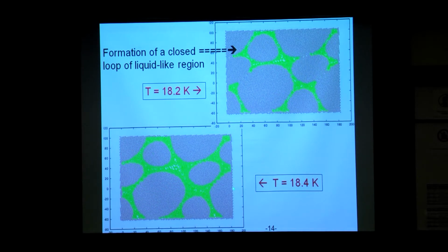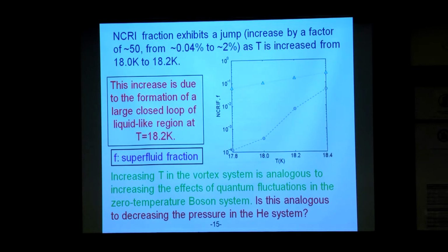As we increase the temperature even further, these loops get bigger, and if we increase it even further, then the whole thing melts. So this is a pre-melting, and the melting is taking place preferentially along the grain boundaries, and because of that, the structures are becoming bigger and they're joining to form bigger structures. So if I now calculate the rotational inertia for such a system as a function of temperature, then I'll get a picture that looks like this. So this is the picture.